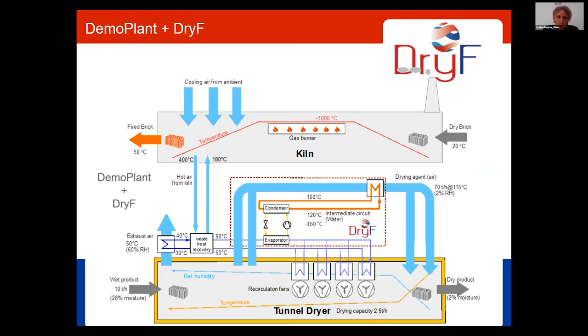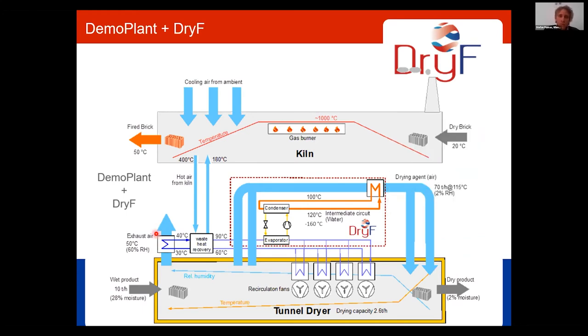and is providing cold water that is sprayed into the cooling tower and the scrubber, where the moist air from the dryer goes through, and we gain warm water of about 40 degrees Celsius. The absorption heat pump lifts this temperature to 90 degrees, and with this water, we go into the dryer. You do not see my pointer, do you? Laser pointer here. So we have here the wet air scrubber. We have an absorption heat pump driven by excess heat from the kiln. It provides 90 degrees of water, and internal heat exchangers in the dryer are used to operate the dryer.